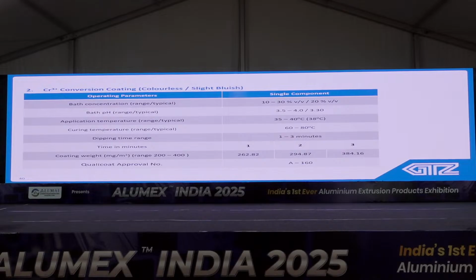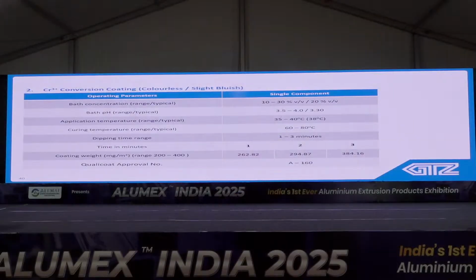And we have done different times for dipping, and this is the coating variation. Lower the time, lower is the coating. And it is Qualicoat approved, approval number is A160. This means all testing after powder coating is passed. That is the cupping test, bending test, all tests after powder coating as per Qualicoat specification are passed.